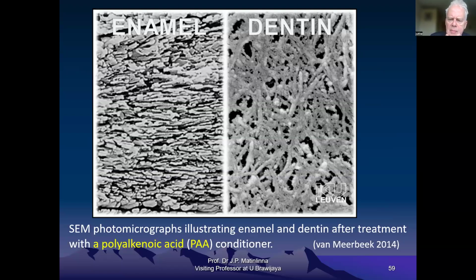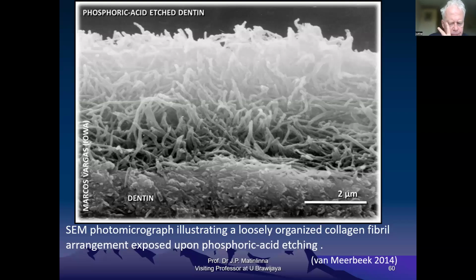I'm here using a few of Professor van Meerbeek's very nice illustrations. So here we see SEM micrographs illustrating enamel and dentin after treatment with polyalkenoic acid conditioner, PAA. So we are not talking about phosphoric acid this time. You can see how the enamel looks after etching and how dentin may look. This SEM picture illustrates a loosely organized collagen fibril arrangement exposed by phosphoric acid etching. So when things go nicely and carefully, we have here the dentin surface and the collagen fibrils, nicely and neatly organized like this.